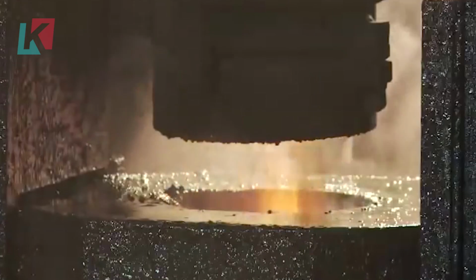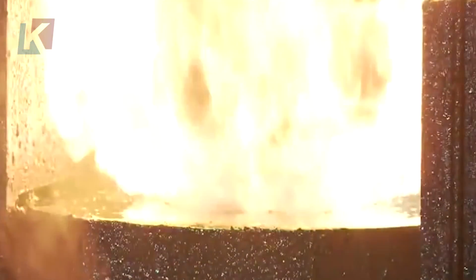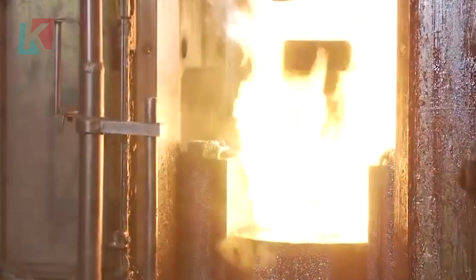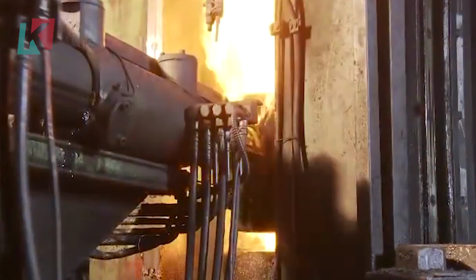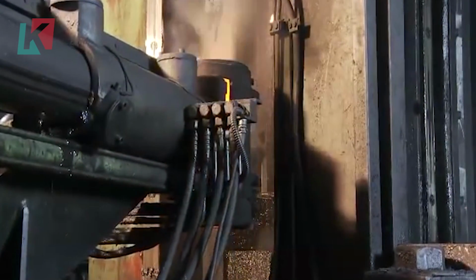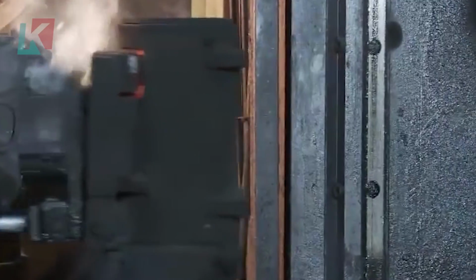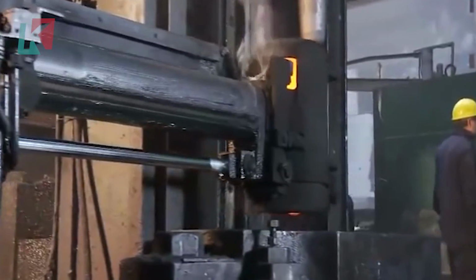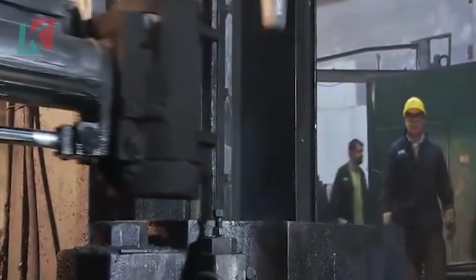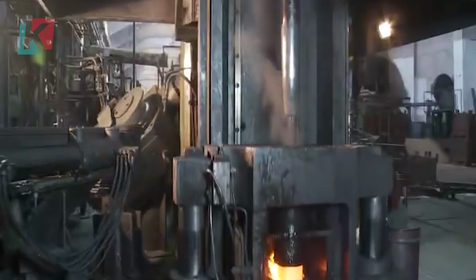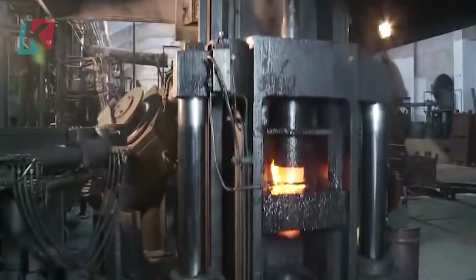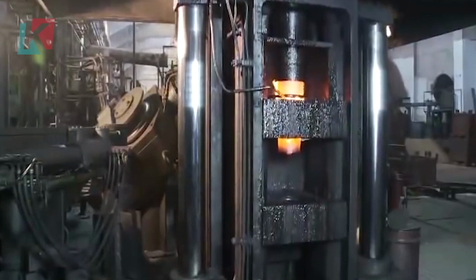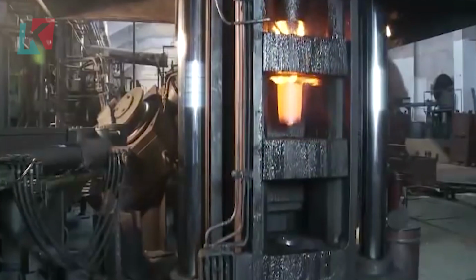The die design is particularly sophisticated. Made from hot work tool steel and heat treated to 48 to 52 HRC. These dies must withstand repeated thermal shock and mechanical stress. The dies are preheated to 350 degrees Celsius to minimize thermal gradients that could cause cracking. During forging, the material flow is carefully controlled to eliminate internal voids and ensure uniform grain structure.